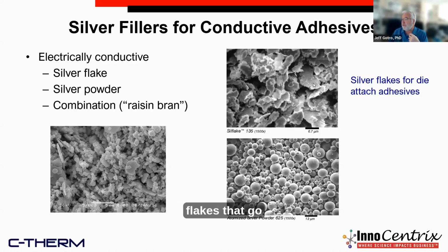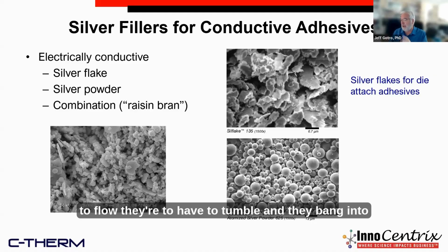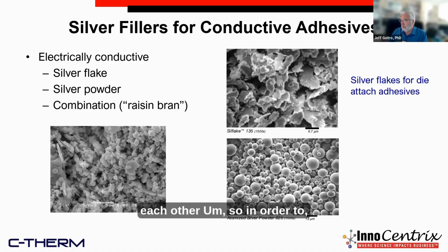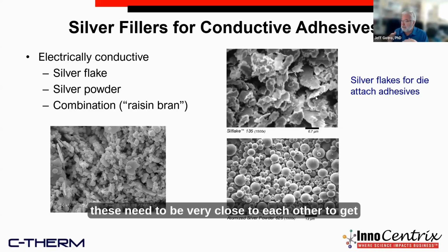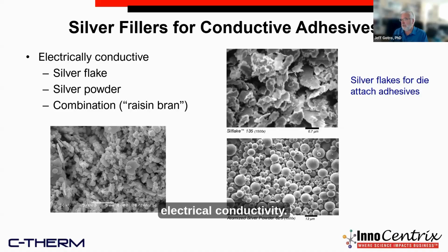So here are the flakes that are used for die attach adhesives, and they're plate-like structures, right? And then here are powders on the bottom, and they're very nice and spherical. So you can think about if we have these encapsulated in a resin, the spheres are going to roll past one another, and it'll flow relatively easily. But if we have these plates, and they start trying to flow, they're going to have to tumble and bang into each other. So in order to help get electrical conductivity, you need to have these plate-like structures, because I'll show you in a minute, these need to be very close to each other to get electrical conductivity.